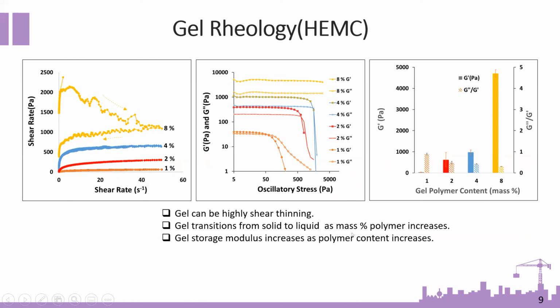Here I bring you a typical example of gel rheological measurements of hydroxyethyl methyl cellulose. You can clearly see on the left side the flow curve of hydroxyethyl methyl cellulose, and as you can see, at all of the concentrations, the hydrogels are shear thinning, and the viscosity increased as we increase the gel concentration.